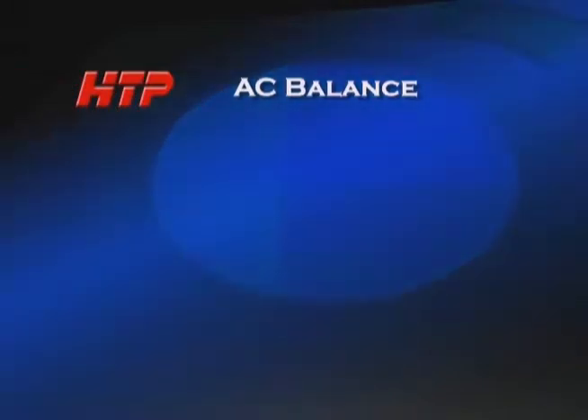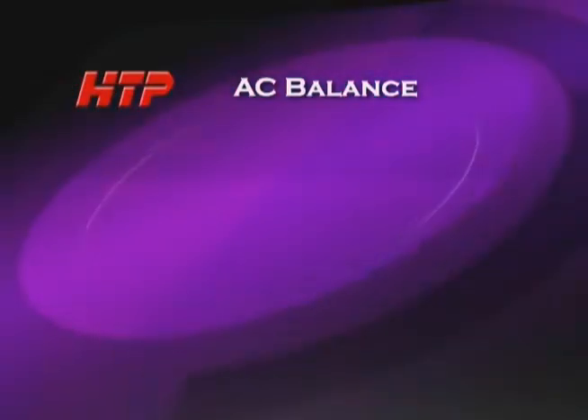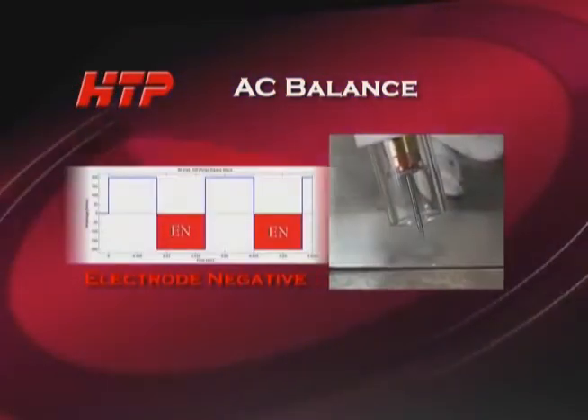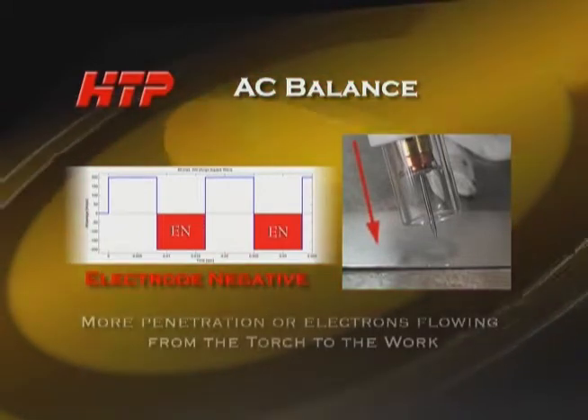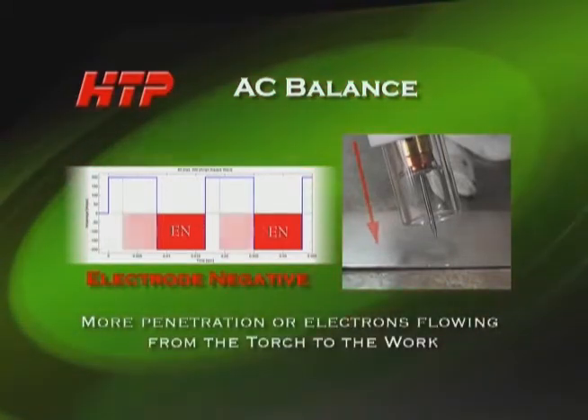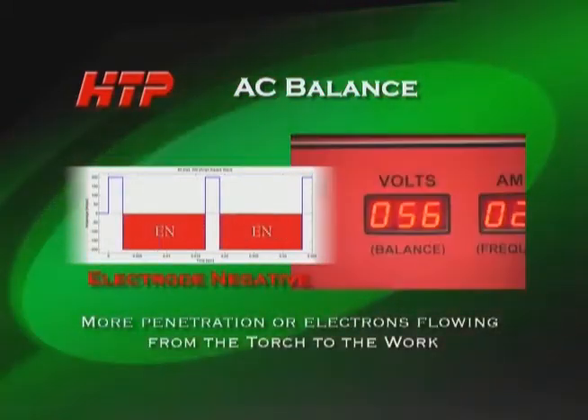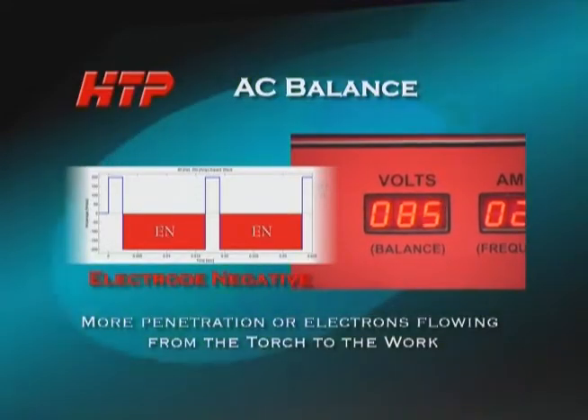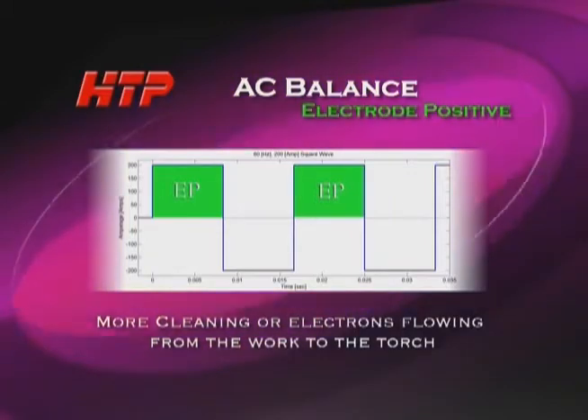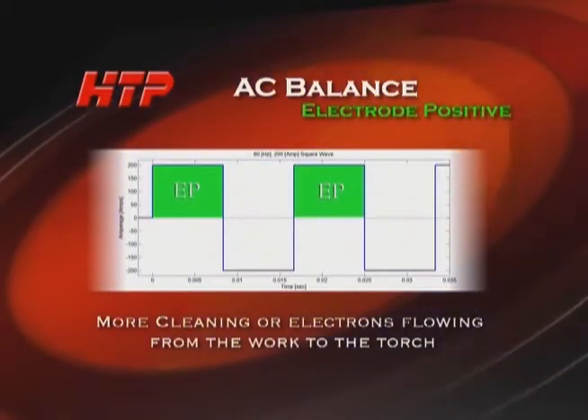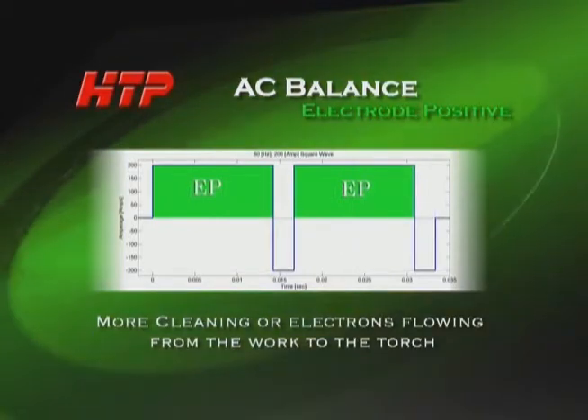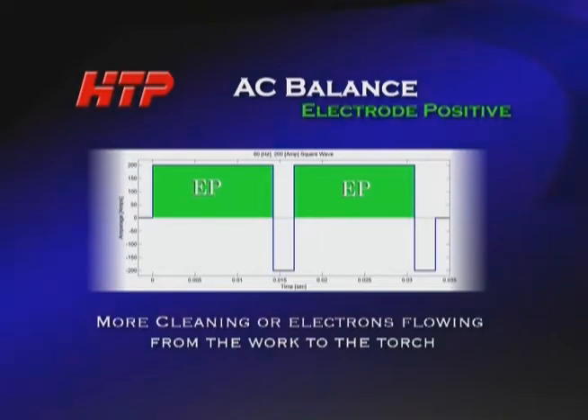In certain instances, such as welding a thick piece of aluminum, we may want more penetration, electrons flowing from the torch to the work, so we increase the AC balance. And in certain instances, such as an oily casting, we may want more cleaning, electrons flowing from the work to the torch, so we decrease the AC balance. The balance control lets us change the percentage of the wave that is electrode negative. So let's look at this again.